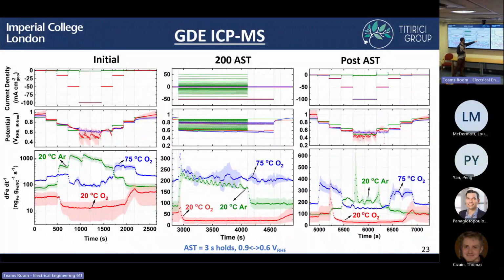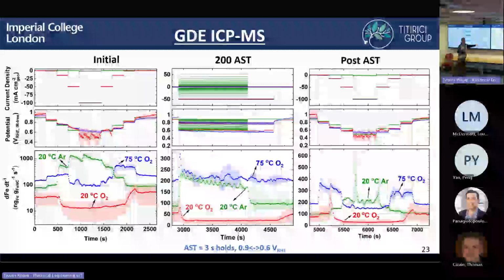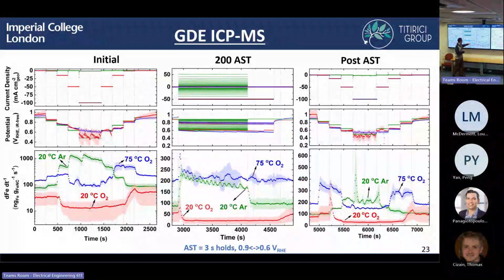And so then when you look at, say, 75 degrees in oxygen, we have a more distinct increase in iron concentration here, because we're dissolving our built up iron oxide into the electrolyte. And you see that as well at 20 degrees, we have this clearer initial increase in iron concentration as we have this buildup of iron oxide formed in the catalyst layer, which then dissolves at low current density, but then starts forming iron oxide again as we go to higher current density.